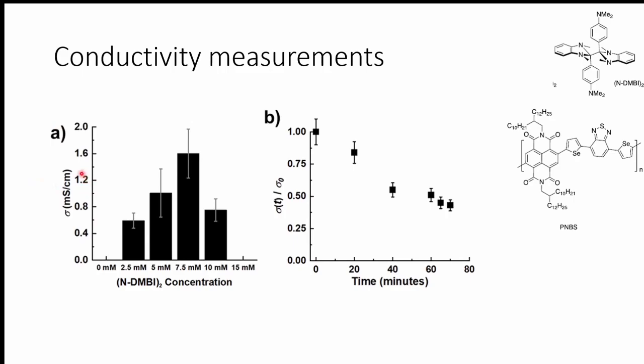Now, if you remember from earlier, I said the conductivity we want for a metallic type is 10 to the power 5. So this is 8 orders of magnitude less than what we want. However, you don't always need the most conductive polymer film in the world, because for certain applications like LEDs, you want it to be just conductive enough. Because if it's too conductive, your charges will migrate too quickly and it might kill your device.